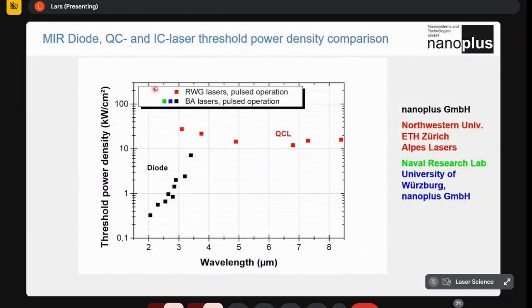When you look at the mid-infrared area, say between 2 and 8 microns, you can see the diode lasers are here between 2 and 3.5 micrometers. And the quantum cascade lasers are starting at 3, going up to 8 and even beyond. The change that you can see in this graph is the threshold power density. The diode lasers at 2 microns have a threshold power density of something like 0.3 kilowatt per square centimeter. And if you go up here, they are in the order of something like 10 kilowatt per square centimeter. Going to the QCLs, all the lasers are in the order of 10 or several tens of kilowatt per square centimeter.